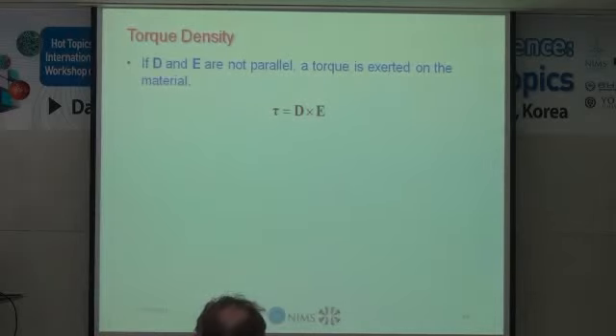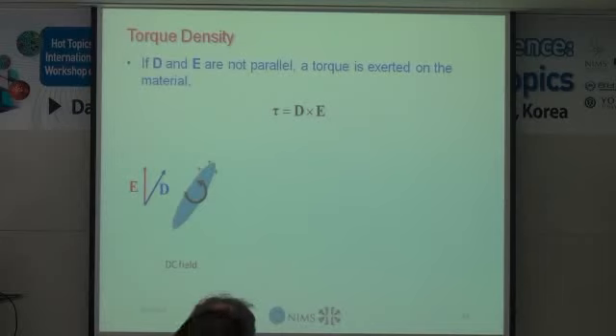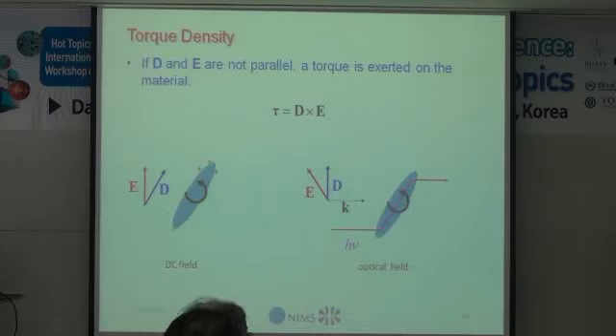And if one looks at the free energy and asks how much work I have to do to rotate the director a little bit, it turns out to be this quantity. This is the torque per volume. It's just D cross E in these materials. If you put the molecule into an electric field, D will not be along the electric field, and this cross product will give you the torque that tends to rotate the molecule to be parallel to the electric field. Interestingly, optical fields also do the same thing.